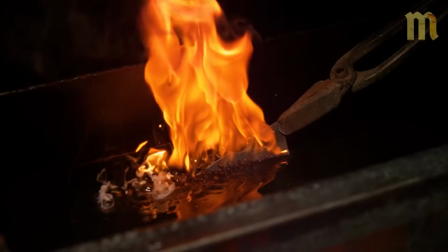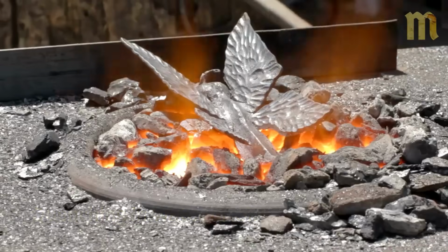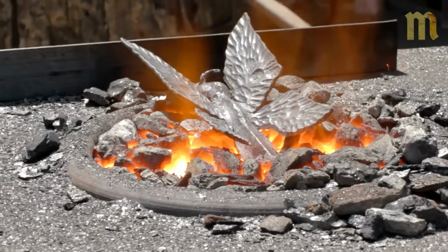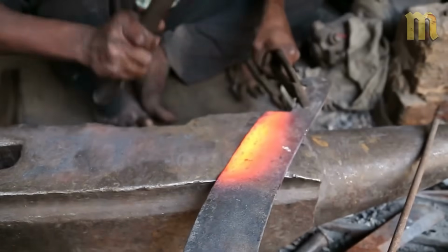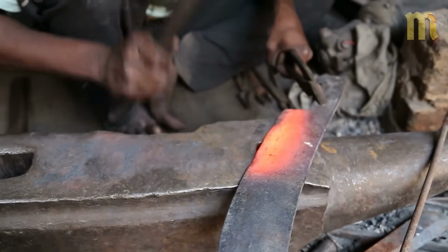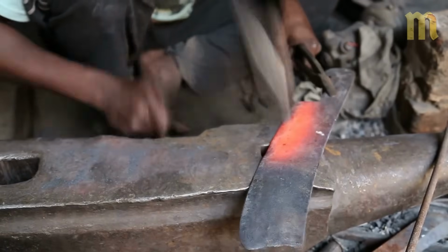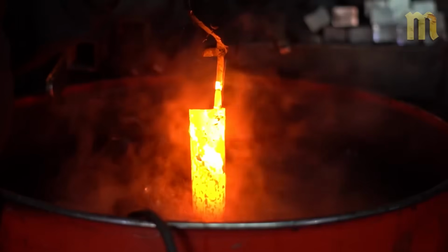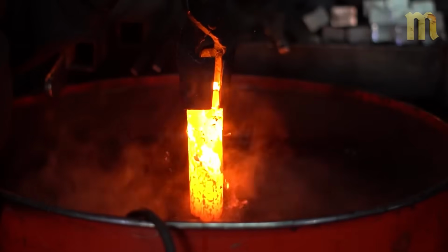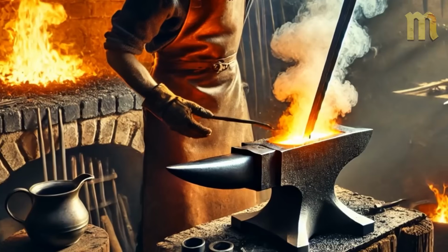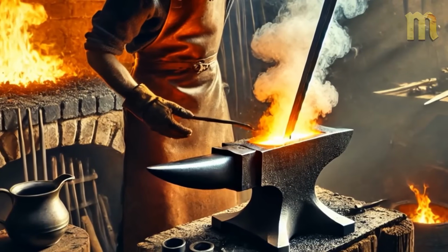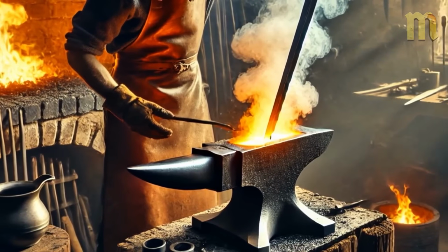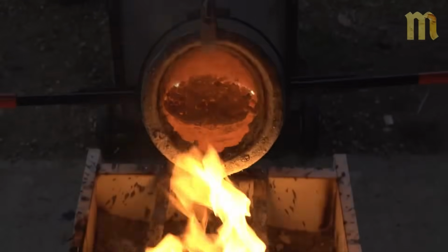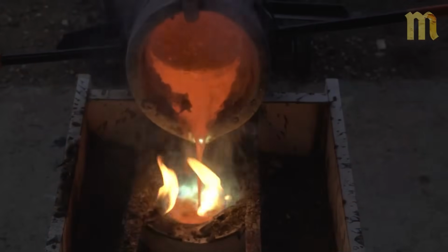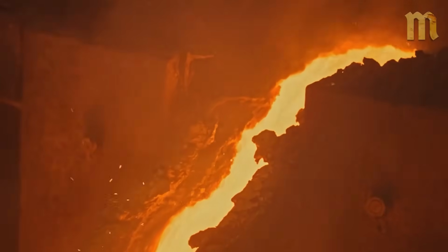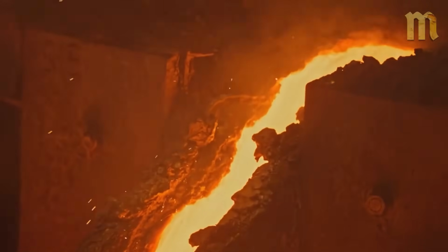The hardening process, quenching in water or oil. Once a blade had been forged into shape, it needed to be hardened. This was done by heating the metal to a high temperature, often a glowing orange or yellow, and then rapidly cooling it, a process called quenching. Water quenching, faster cooling resulting in a very hard but brittle blade. Oil quenching, slower cooling, making the blade slightly softer but much tougher and less prone to breaking. Blacksmiths could judge the temperature of the metal just by its color, a skill that took years to master. If the blade was overheated before quenching, it could warp or crack, ruining hours of work.